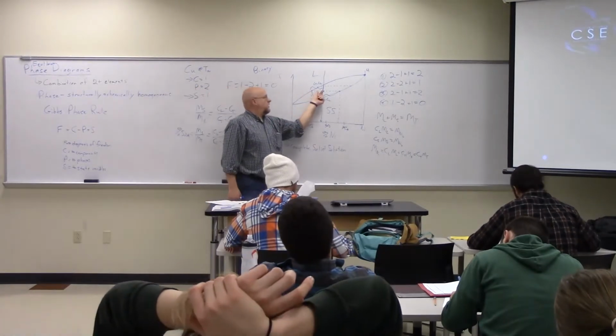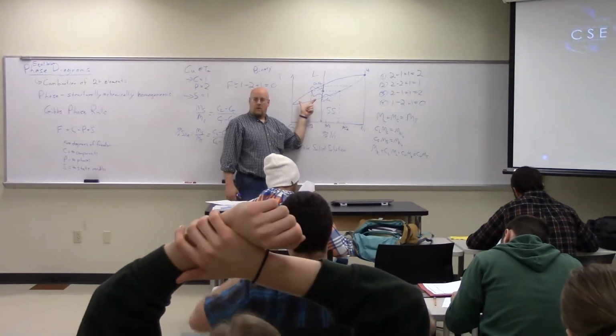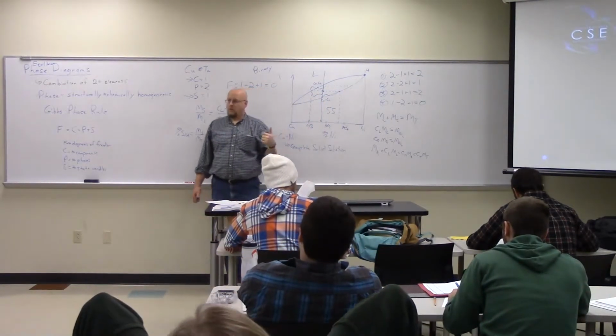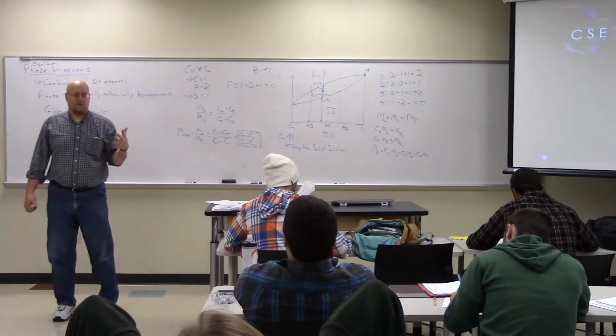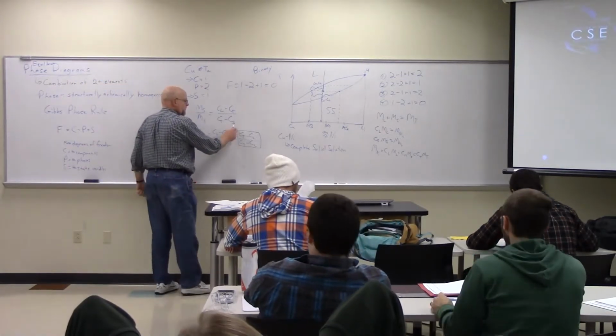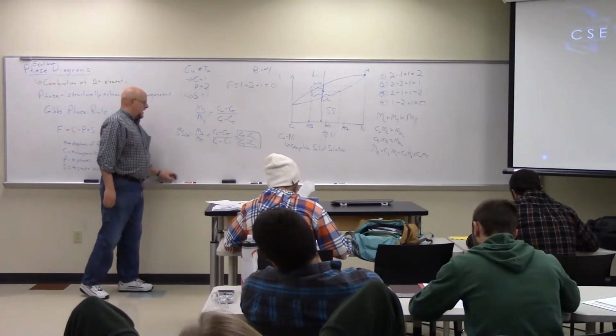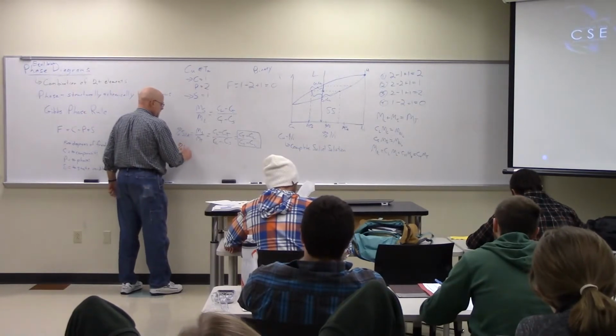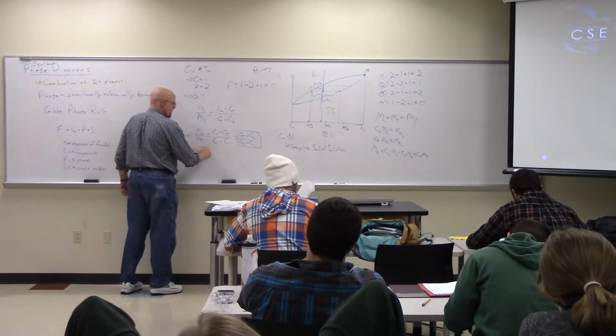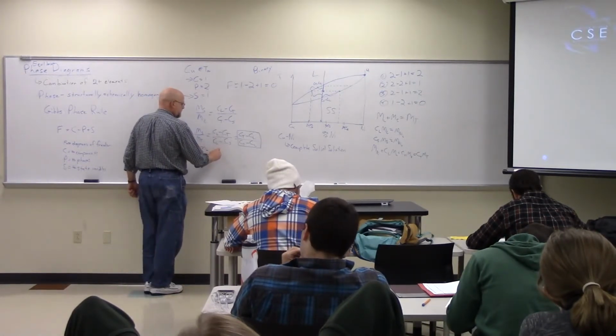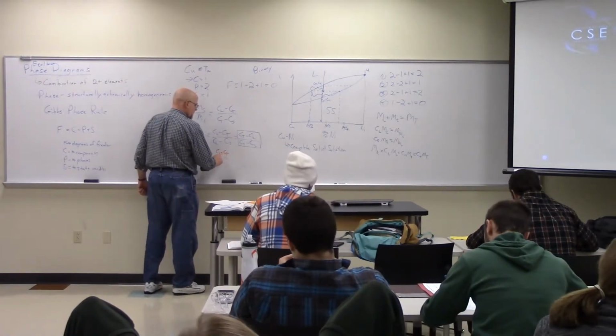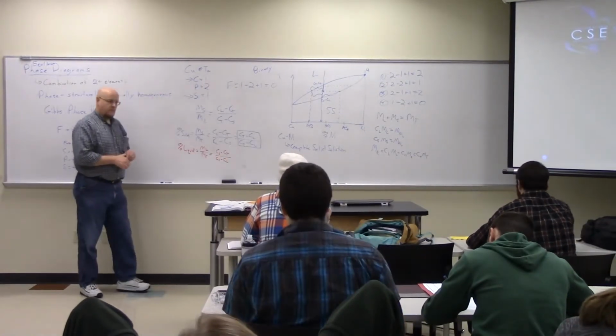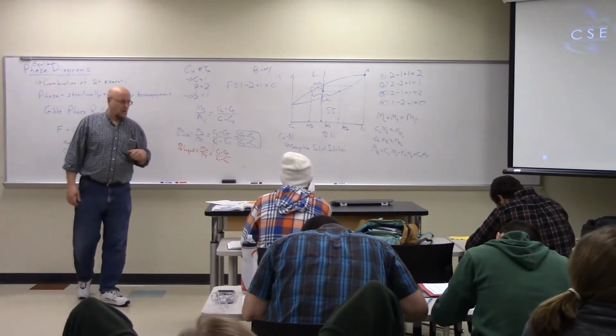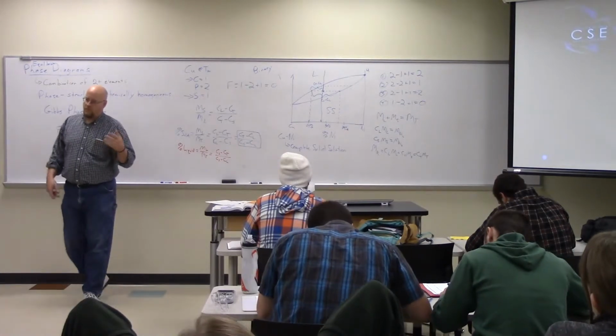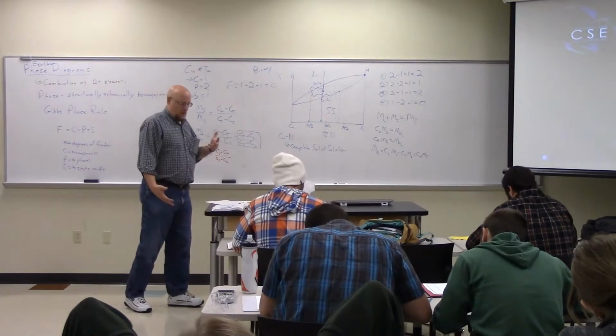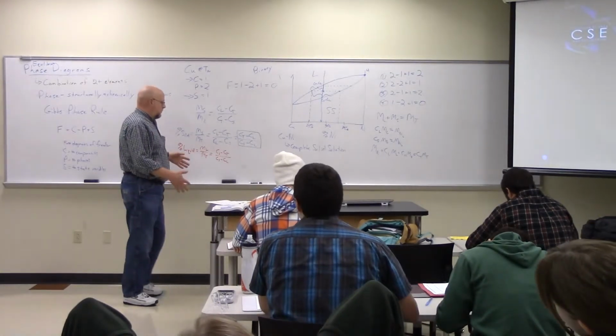And as I progress down here, this side grows, so the solid percentage grows. And this side shrinks, so the liquid percentage shrinks until I get down here, it's all solid. Kind of follow that conceptually? Okay? So the key is just to recognize the inverse lever rule. The percent solid is that, and similarly, I could write that the percent liquid is equal to the mass of the liquid divided by the total mass, and that's Cs minus CT over Cs minus CL. Okay. So we use this to find out how much of each thing we have. As we start talking about microstructures and such, this will become more particularly valuable.